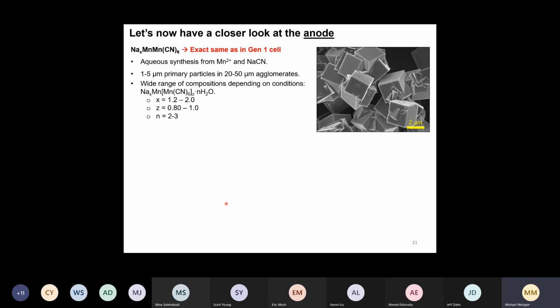So it's a sodium manganese hexacyanomanganate material: sodium, Mn, Mn, CN6. And it's also made in an aqueous synthesis, so a very cheap process using low-cost materials. We get about 1 to 5 micrometer primary crystals here, which agglomerate in these larger structures. In general, they can synthesize a quite a variety of conditions here. Again, this is our general formula, which I think we understand quite well by now, where this X value denotes the intercalated sodium in the material, which can be between 1.2 and 2.